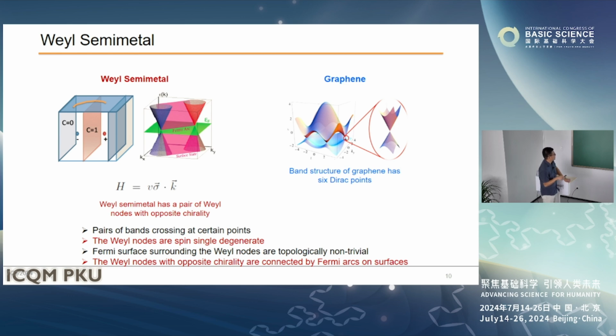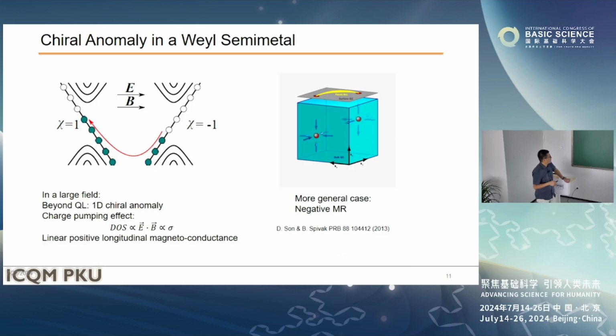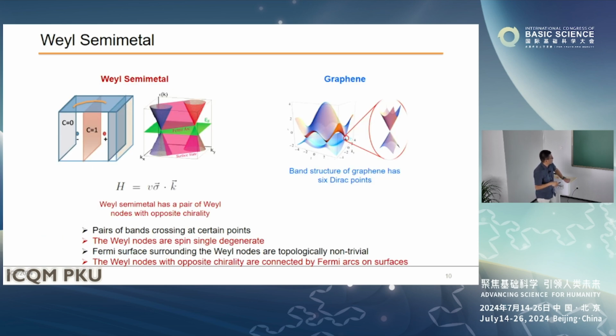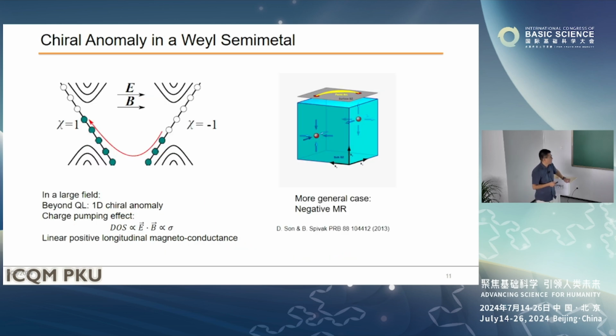Meaning, if you check the surface state of the Weyl semimetal, you find a partial Fermi surface, meaning you have a Fermi arc instead of a loop. So this is a very exotic feature people can imagine. Another point: for those Weyl semimetals, according to high energy physics, you can find an ABJ anomaly in a Weyl metal. What is that? Meaning if you apply a magnetic field and electric field to solid materials